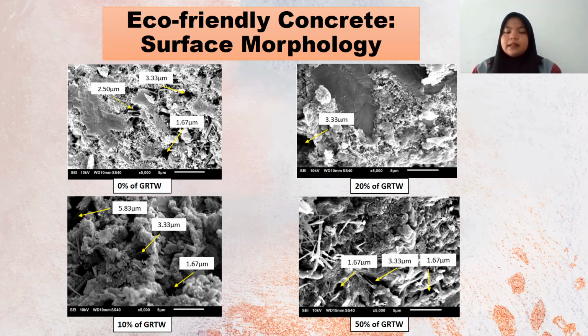Based on the comparison of the microstructure of concrete mix, it is clear that the hydration process in the mix with supplementary material was different from the conventional concrete mix. In the mix of 20% GRTW, the hydration process was quite similar to the normal concrete mix, but development of calcium silicate hydrate gel in the mix was quite lesser compared to the normal concrete.